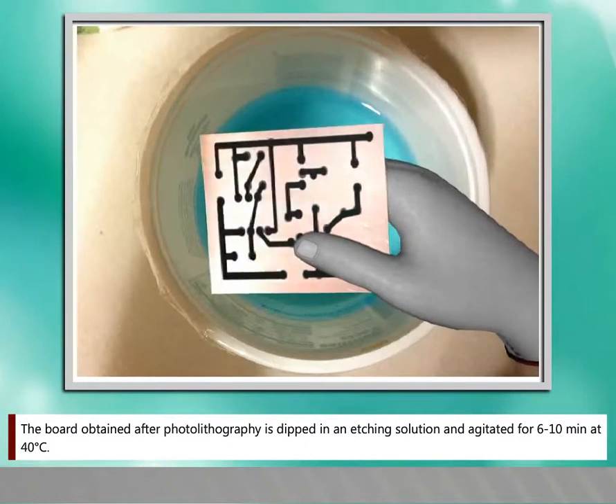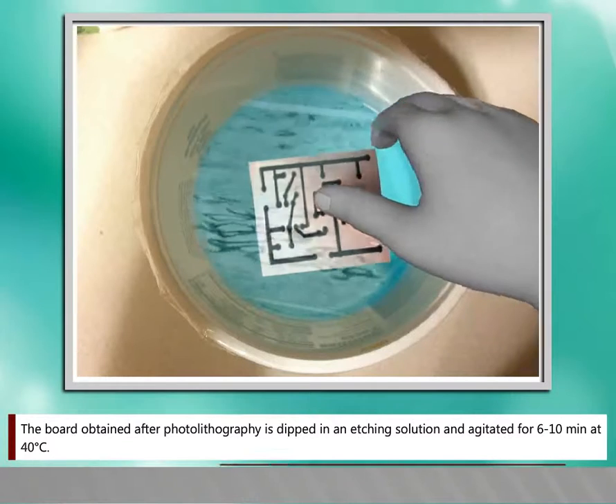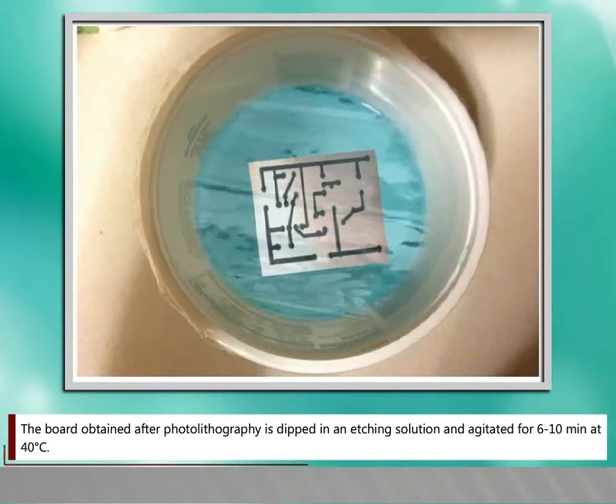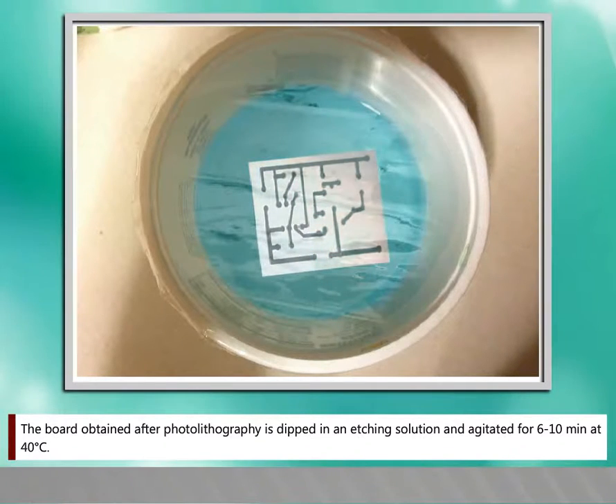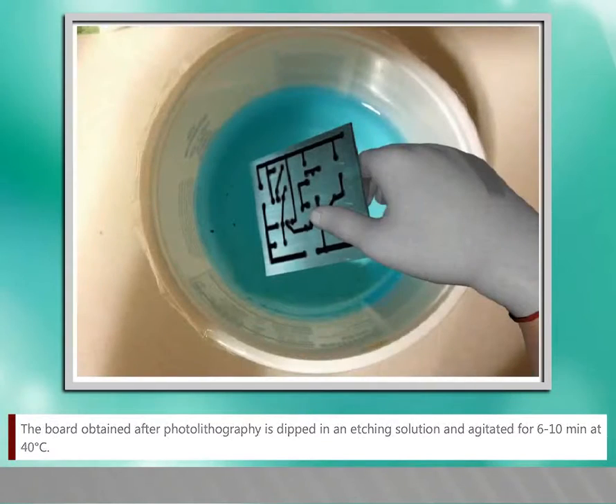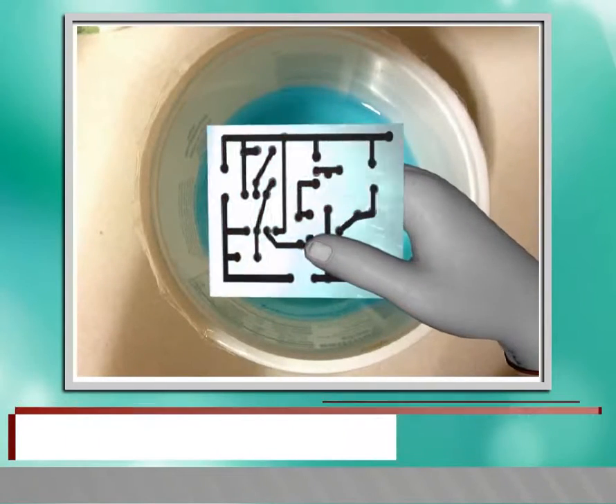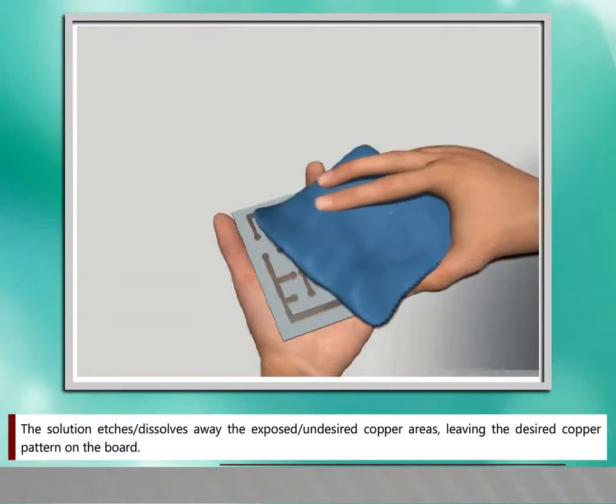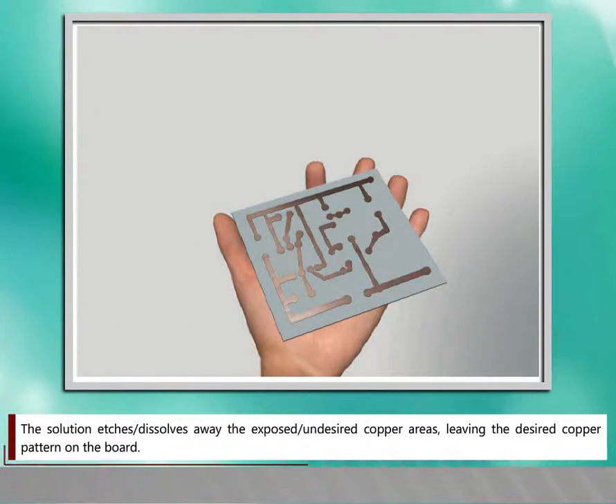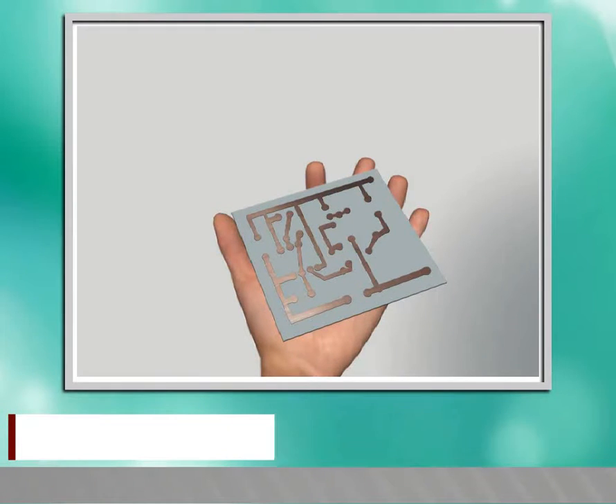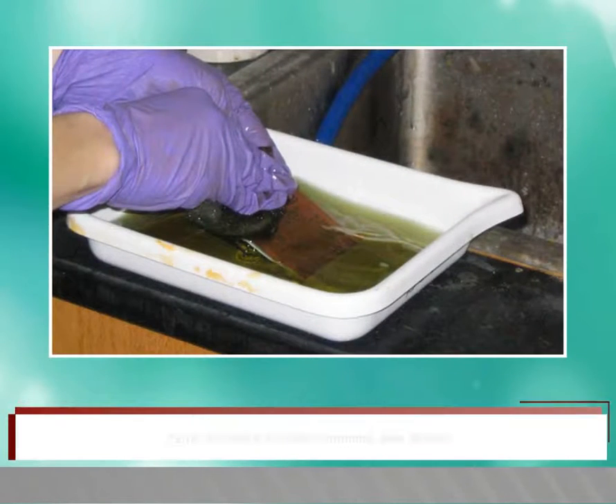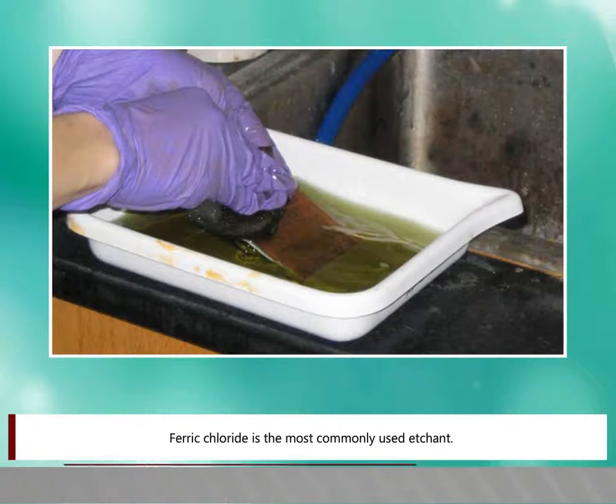The board obtained after photolithography is dipped in an etching solution and agitated for 6 to 10 minutes at 40 degrees Celsius. The solution etches or dissolves away the exposed or undesired copper areas, leaving the desired copper pattern on the board. Ferric chloride is the most commonly used etchant.